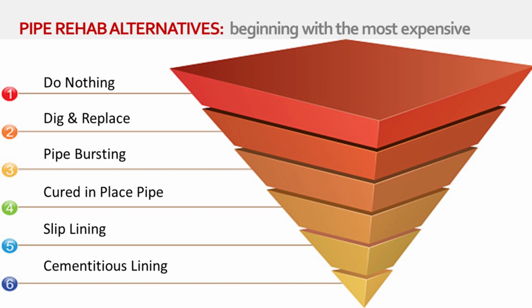As the existing pipe diameter increases, the bag for the CIPP gets thicker and heavier, and as Eric was talking about, it gets to where it requires a lot of equipment to move it around, and requires a large footprint. And he also addressed that it does not address the voids in the invert. And just to go along with that, the equipment that we use to apply the liner, we can use to pump grouts and fill voids with the same equipment. So we're not having to do something different here.